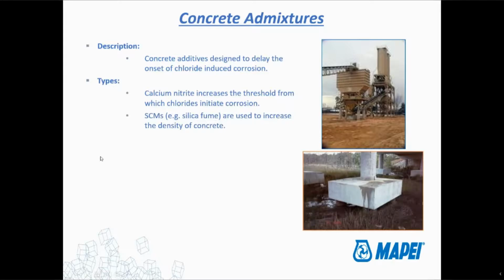Generally, calcium nitrite is what is added to the bag or the mix. That's pretty typical. It's the most effective. That's what everyone is pretty much using across the board. But when you add calcium nitrite to the mix, basically all that it does is increase that threshold. So that 330 parts per million, it raises it up to, say, 500, 600, 1,000, whatever. It's going to depend how much calcium nitrite you add, how much it raises it by. But again, you're hoping to just delay corrosion as long as possible. So the longer you can delay it, the longer theoretically the life of that structure would be.